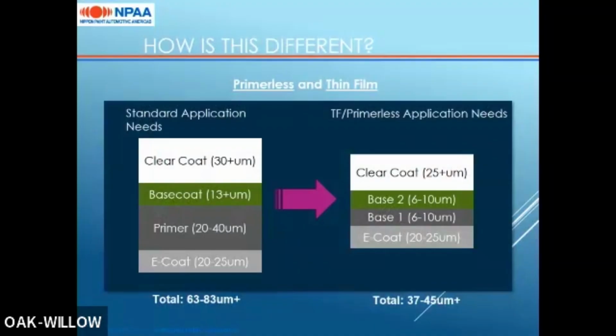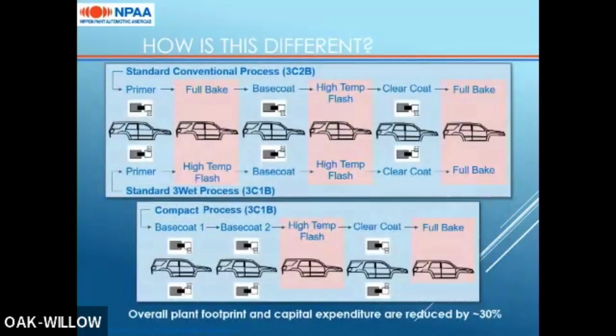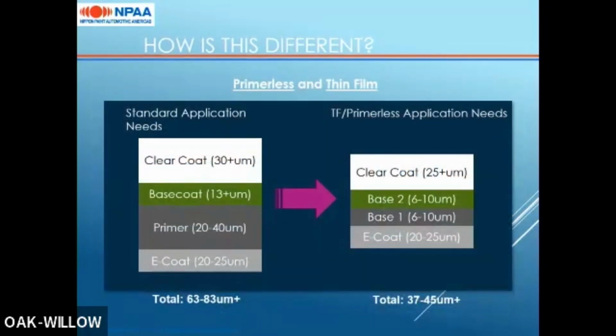So this takes the standard application layering where primer is used, typically at 20 to 40 microns depending on the technology, base coat of 13 or more microns, and clear coat of 30 or more microns. So a total top coat film build of 63 to 83 microns.